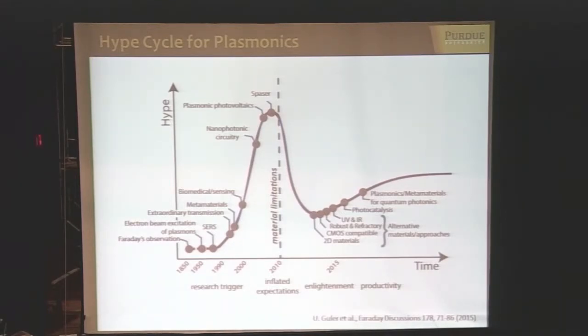Surface-enhanced Raman scattering indeed was very important, particularly the fact that this dramatic enhancement - many orders of magnitude enhancement in Raman scattering - is related to high local fields associated with surface plasmons, as was pointed out by Martin Moskovits. That indeed was very important.